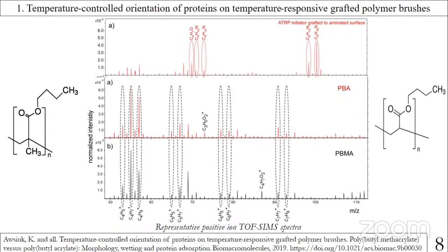I want to present you three of my past projects. First is temperature-controlled orientation of proteins on temperature-responsive grafted polymer brushes, such as polybutyl methacrylate and polybutyl acrylate. The composition of grafted brush coatings was determined using time-of-flight secondary ion mass spectroscopy. This is a representative positive ion ToF-SIMS spectrum, which confirmed that polymerization was successful.